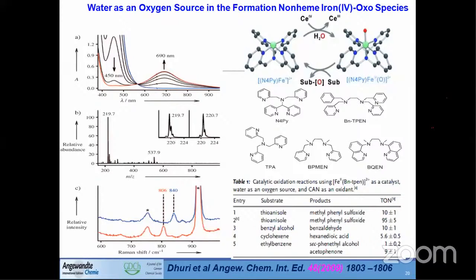But now I used water as an oxygen source to generate iron-oxo species. This iron-oxo species was well characterized by all techniques, including UV, NMR and all those things. Whether this oxygen is really coming from water, we also checked by taking H2O18. When we did that, we could see the labeled oxygen here. Instead of O16 we got O18, so everything was confirmed.